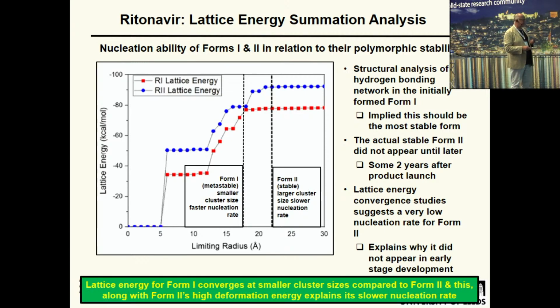What comes out is that the lattice energy of Form 1 converges at smaller cluster size compared to Form 2. And this, along with Form 2's high deformation energy, explains its lower nucleation rate. It's just a slow nucleating system. When it gets there, it's there with you, and as they found out to their cost, you can't get rid of it.